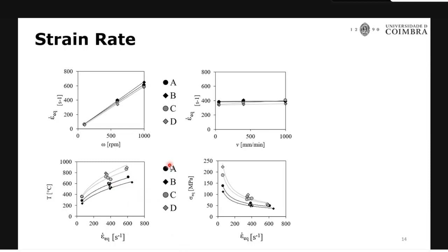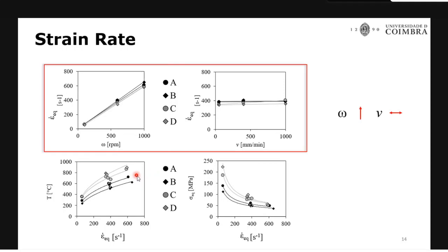You can also see that with respect to the material property, the harder material shows higher temperature because it involves higher torque and higher friction forces. So naturally it is attaining higher temperatures. And while plotting the relationship between the flow strength and the strain rate, we can see that at a higher strain rate, the flow strength of the material will be very low, which can be correlated with these temperatures.